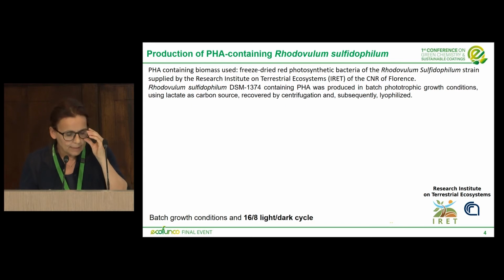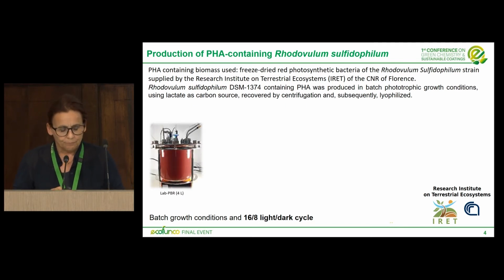So, now, okay. The biomass used has been supplied by the Research Institute on Terrestrial Ecosystems of the CNR of Florence. We have collaborated with this institute for many years. And in this case, we have a photosynthetic purple bacteria containing PHAs. It was produced in batch phototrophic growth conditions under 16 hours light and 8 hours dark cycles, in view of the experimentation outdoors, and using lactate as a carbon source. And after 120 hours, the biomass was recovered by centrifugation and subsequently lyophilized.